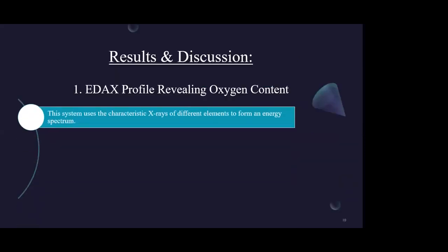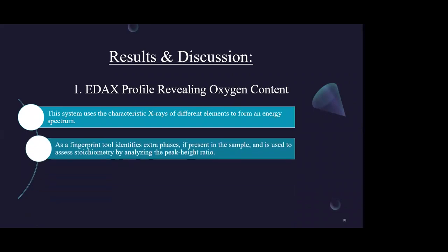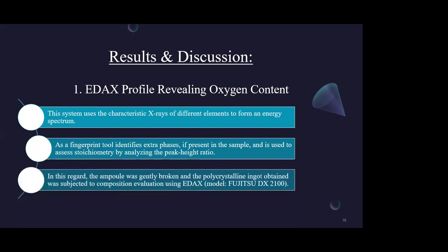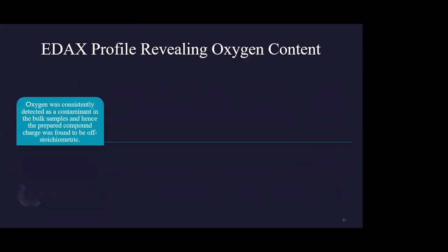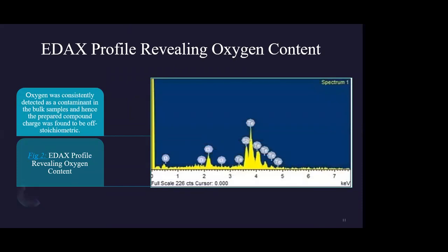But when I analyzed the EDX profile revealing oxygen content, the system uses the characteristic X-rays of different elements to form an energy spectrum. As a fingerprint tool, it identifies extra phases and is used to assess stoichiometry by analyzing the peak height ratio. In this regard, the ampule was gently broken and the polycrystalline ingot obtained was subjected to composition evaluation using EDX. So this one, the graph clearly shows the presence of oxygen.